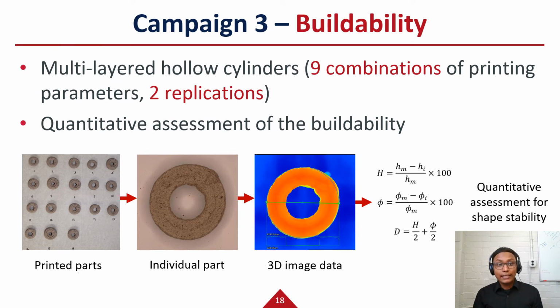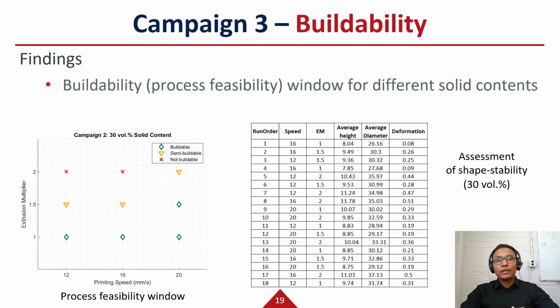Therefore, we quantitatively evaluated the deformation of the printed parts compared to our model design. Here, h and phi are the measures for deviation along the height and diameter of the multi-layered cylinders that we printed, and d is a measure for cumulative deformation. Here is a sample calculation for 30 volume % solid content. The deformation gives us a comparative assessment of the shape stability of the material for different printing parameters. The lower the deformation, the better is the shape stability of the material for a specific combination of printing parameters.